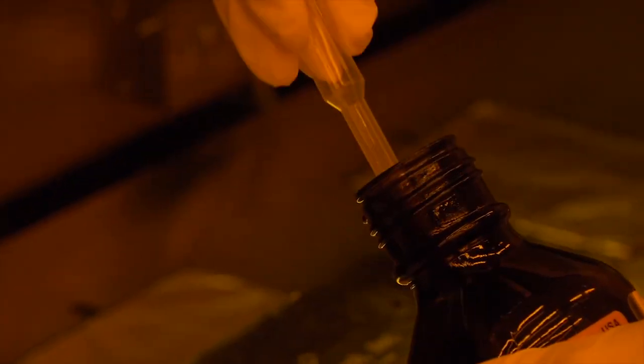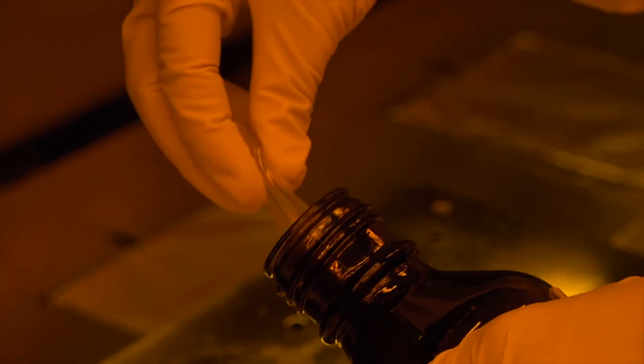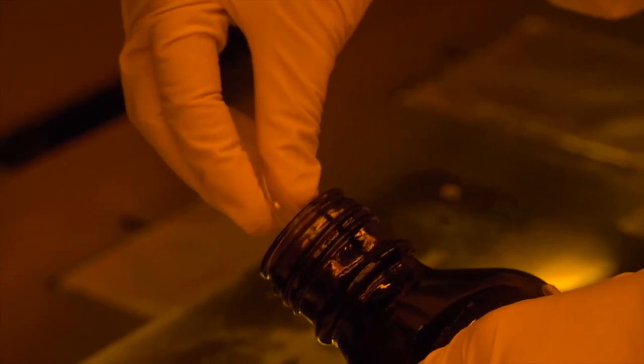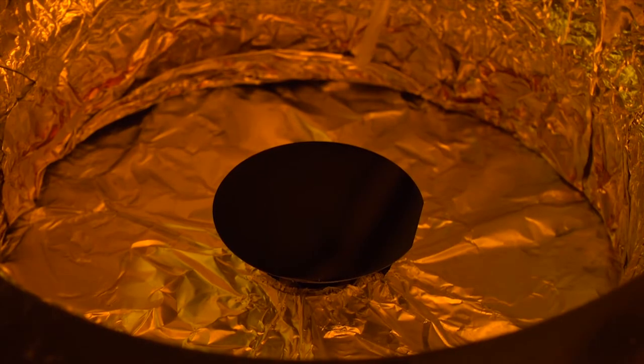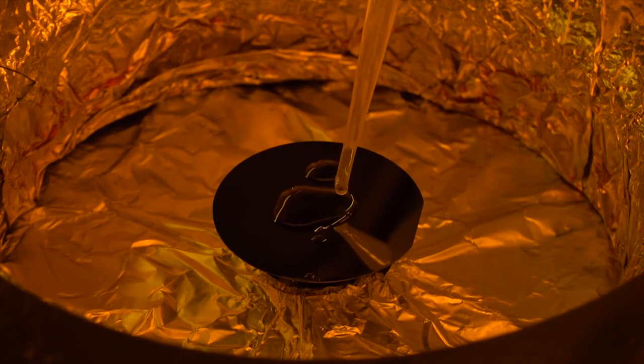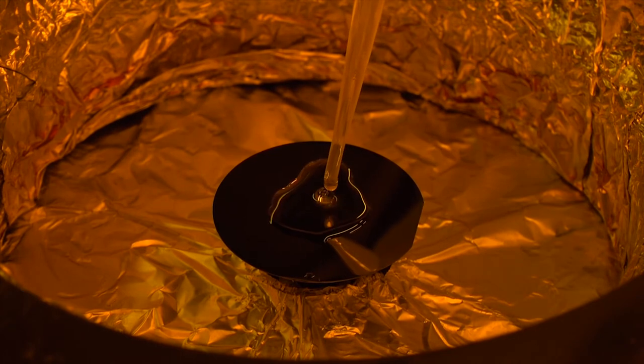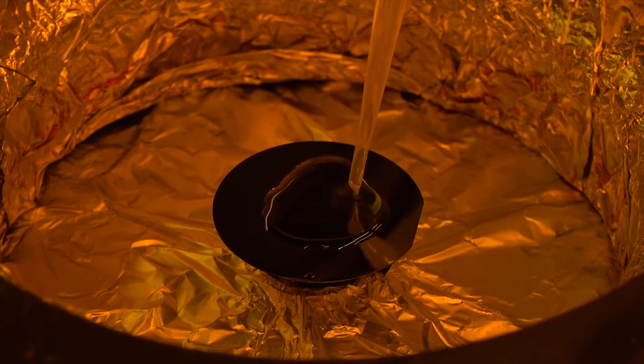we will spin the wafer at 5000 RPM for 40 seconds. We are now ready to spin the EBL resist. We use a small plastic pipette to take a few milliliters of resist from the bottle. Next, we pipette the EBL resist onto the wafer, right in the middle.